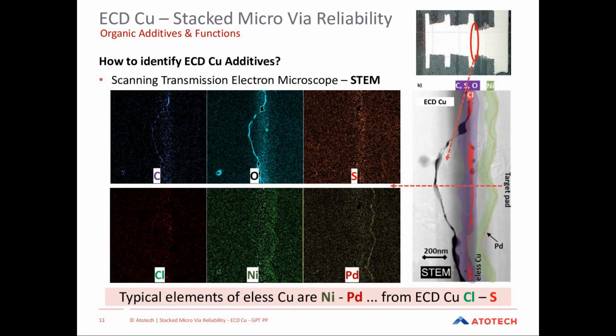But when you find chloride, sulfur, or nitrogen, then it's already much more likely that these are impurities caused by the electroplating copper process. And here you see now an example of how to analyze the co-deposition and adsorption of organic additives at interfaces. Here you see a stacked via build-up, and you see an area where the integrity is disturbed.